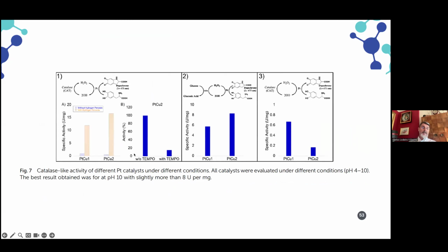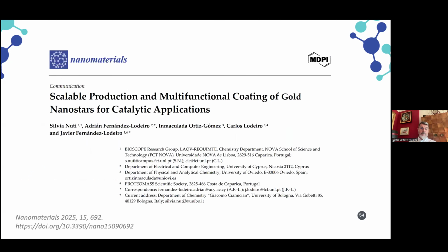As I showed you, they show the same properties of catalytic activity depending on the pH. pH 10 is the best to perform these properties with this material, and then we can use it depending on where the platinum is located. We can observe that with a higher percentage of copper in the platinum planes, we obtain better activity, and we increase the velocity.